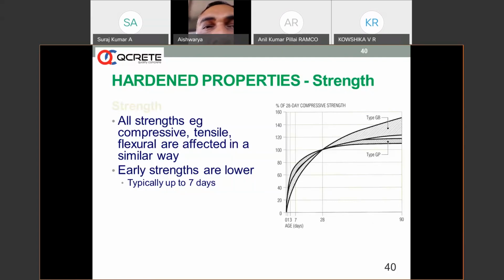So the initial strength gain, when you are using OPC plus PFA or OPC plus GGBS mixes, is a bit stunted, and over time after 28 days you can see the curve moving up, and you can see a big gap maintained between OPC plus PFA or OPC plus GGBS mixes against the normal OPC concrete. This is a significant benefit a person who orders blended concrete gets actually.